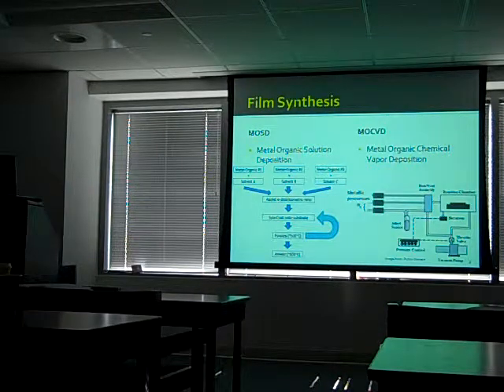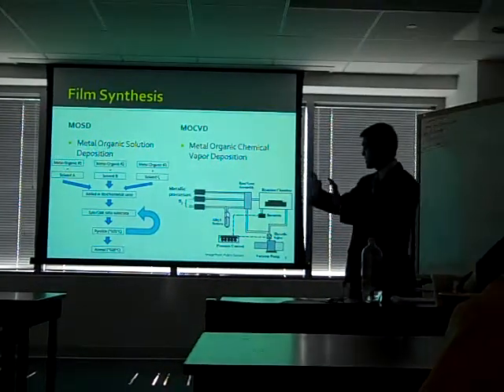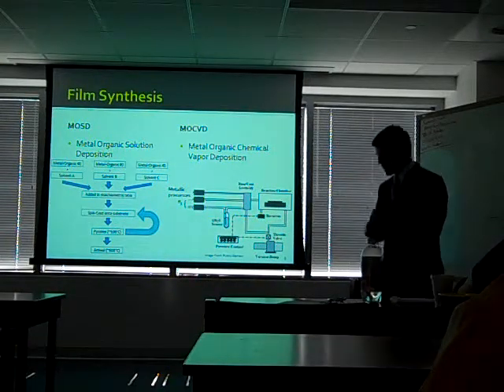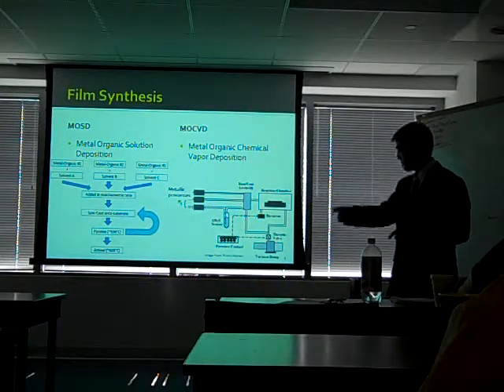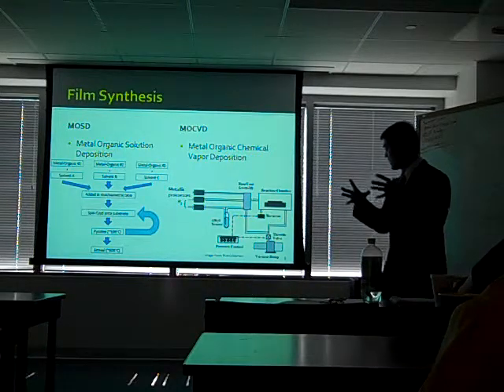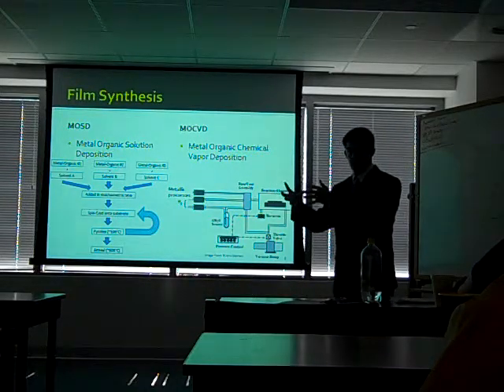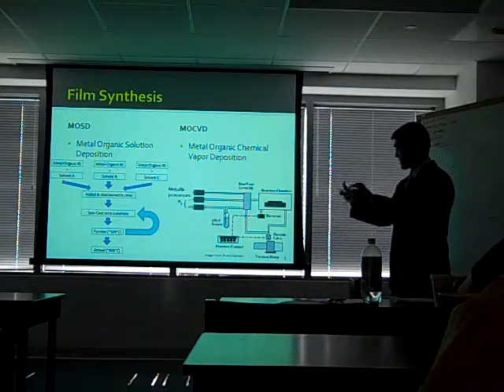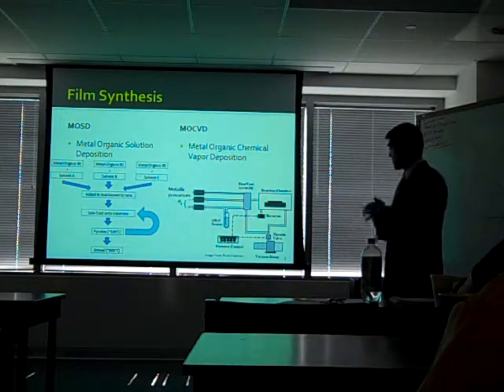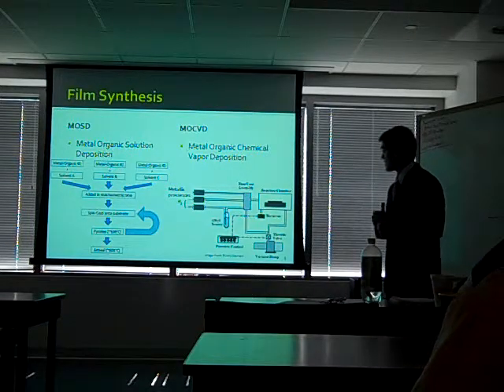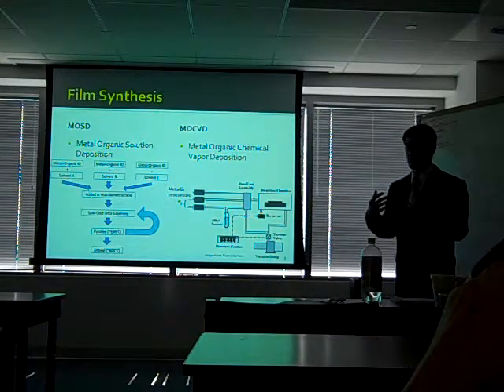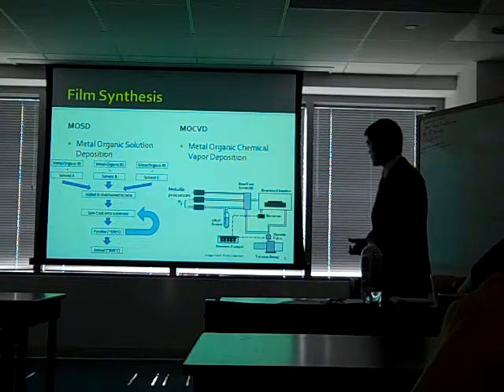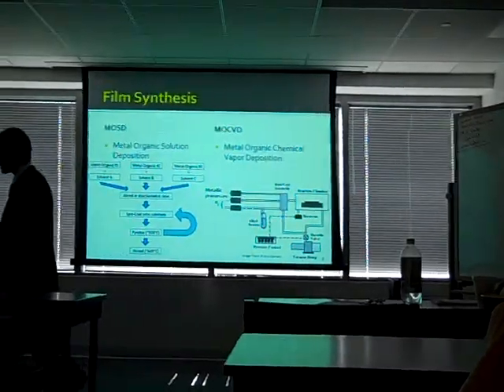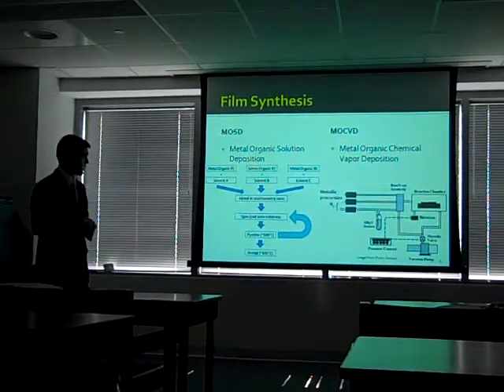Now, MOCVD is the scale-up method of choice for these films. It works by metallic precursors in the vapor phase being pushed by an inert gas, controlled by a computer, an input controller, by mass flow controllers, and the vapor is introduced into the high vacuum reaction chamber. The reactants react, and they condense onto the substrate. An advantage to using this is that the films grow epitaxially, so there's no need for subsequent annealing because the films are already crystalline. And again, MOCVD is an industry standard technique, and so it would be the scale-up method of choice.